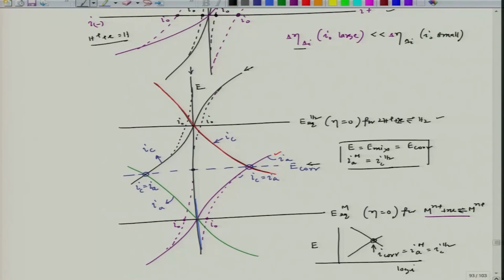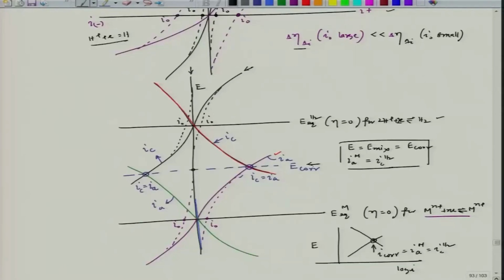But remember, this is for two different processes. One is the rate of cathodic reaction, which indicates the rate of hydrogen evolution reaction on the metal surface, and the rate of anodic reaction indicates the metal dissolution rate, and that is what we get in this steady condition. So, now if I take a small voltage perturbation around this, let us say this is my small voltage perturbation, which is del E.